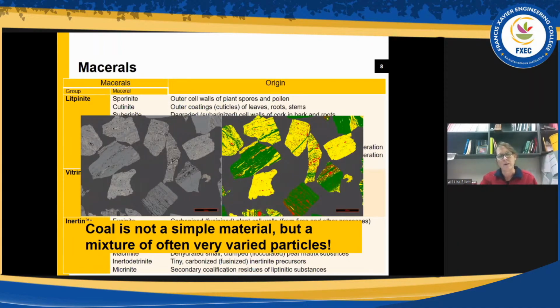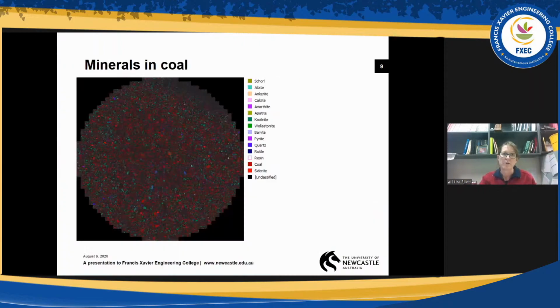To add on top of that, within those coal particles, there's also minerals. So if we have a look at this, this is an SEM image of a coal sample. You can see the dark red material is coal, the carbonaceous material. All the other colours are the minerals in the coal. Now, it's not a consistent colour across it, so that shows you that the minerals are there in individual particles or in particles on their own where they've been liberated from the carbon material during crushing. So again, you can't look at a coal and say it's an average material. Every bit changes, and you really have to be considerate that it's a heterogeneous material.